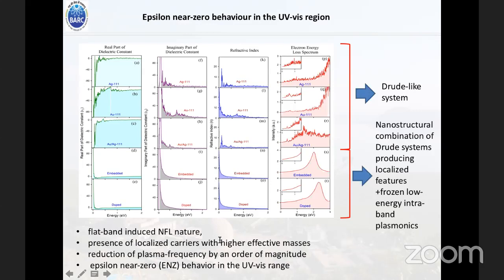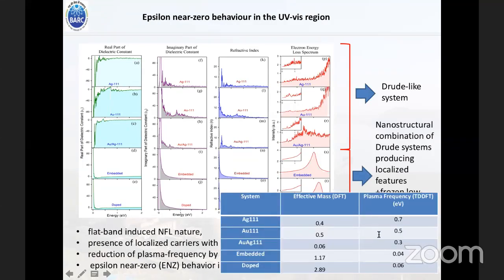So we are having a flat band induced NFL nature here, presence of localized states, reduction of plasma frequency, that I'll be showing in the table. And then there is epsilon near zero behavior near the UV-vis range. And if you look at the plasma frequency here, there is an order of magnitude decrease for the plasma frequency. As I have told you, the plasma frequency has an inverse proportionality with the effective mass.